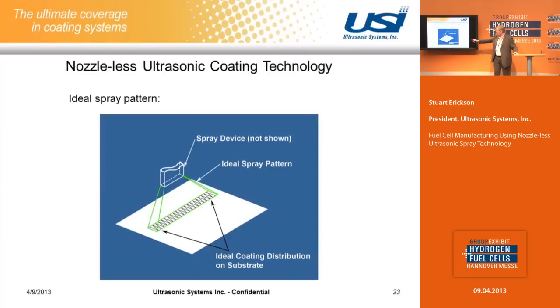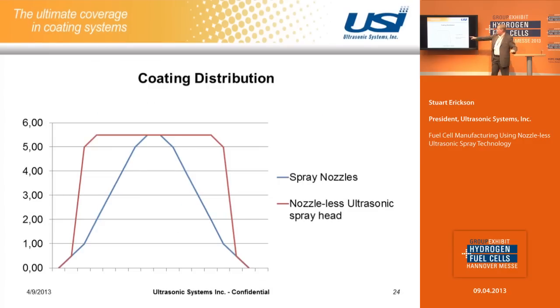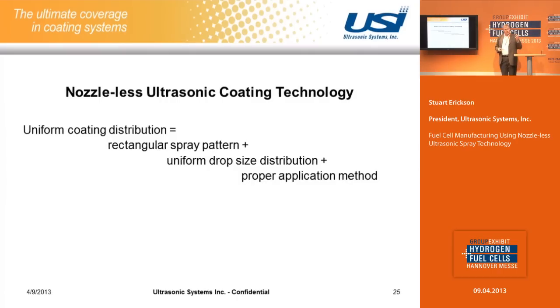So ideally, our spray device makes a pattern like that, which would make a rectangular coating on the substrate. Again, if you're comparing a rectangular spray pattern versus any type of spray nozzle, you're going to have a much more uniform distribution across the width of the pattern, whereas any type of spray nozzle is going to have more of a parabolic shape, with more in the center and less on the edges. So basically, the idea to get a uniform coating distribution is that you need a uniform rectangular pattern, plus a uniform drop size distribution, plus the correct recipe, the correct application pattern.